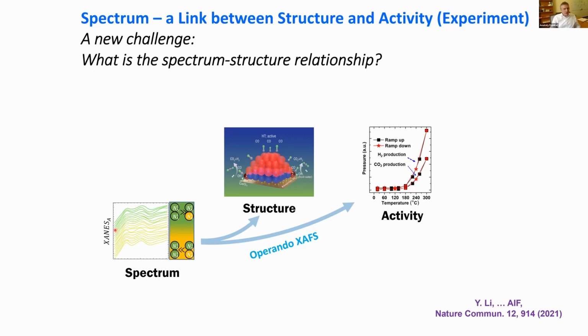And so the alternative is, let's rely on the spectrum as the source of information for the structure and activity. Because if you measure the spectrum, such as an X-ray absorption spectrum, in an operando experiment, you can measure both of them in the same condition. So that sounds promising, but the spectrum and the structure contain different information. The actual material has atoms, and each atom has X, Y, and Z coordinates. So if you have a particle consisting of, let's say, 40, 50, 100 atoms, you have a lot of information stored in it. But in the spectrum, you can't expect that it will give you X, Y, Z coordinates of all atoms. So you need to really understand what information is encoded in the spectrum.